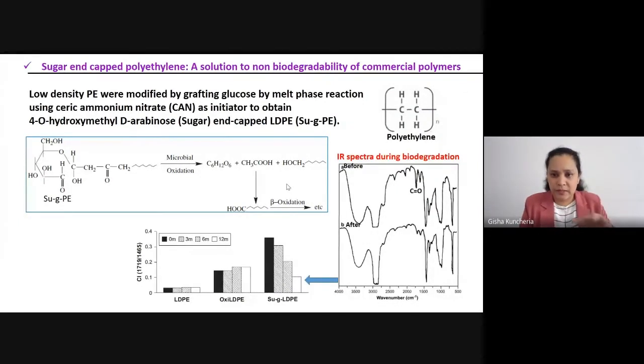Because of this non-biodegradability, I tried in my PhD work to find a solution for the non-biodegradability of polyethylene type polymers. What I have done is I modified the polyethylene by grafting highly hydrophilic molecules like glucose by melt-phase reaction using ceric ammonium nitrate. This glucose is hydrophilic, so it is a good nutrient for the microorganisms. So now my product is sugar grafted polyethylene.